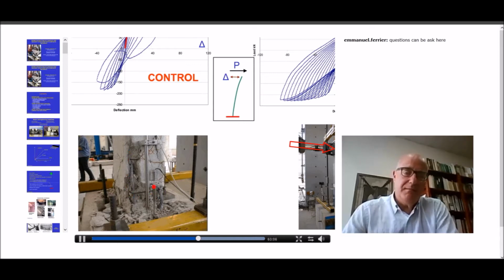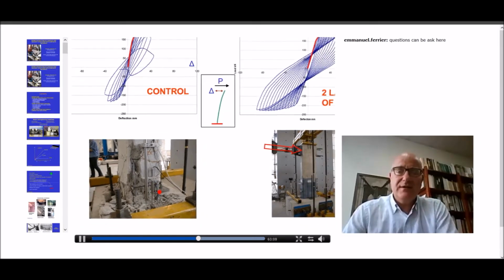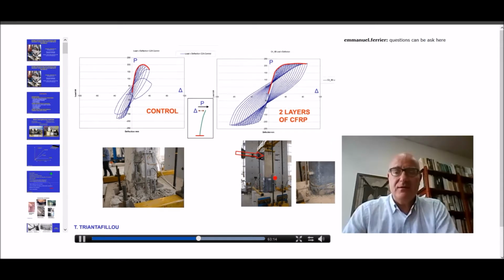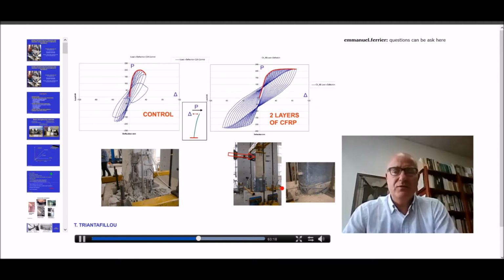We have spalling of concrete, local buckling of the longitudinal reinforcement, which is not the case if the member is wrapped with this local jacket with carbon fibers at the base. Those carbon fibers would fail due to tensile rupture. So by comparing the response of the two, we conclude that again, there is practically no difference in the strength. However, there is a tremendous increase in deformation capacity. Ductility goes really high. I am not sure that everybody is able to read numbers. I can assure you that the drift values are quite high. We are talking about horizontal displacements in the order of 100, if not more, millimeters, corresponding to a column height in the order of 1.6 meters. So that's a very high drift.